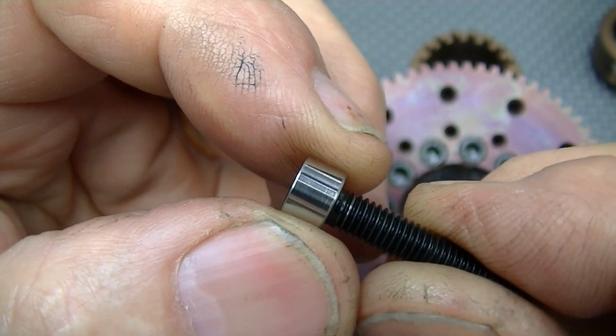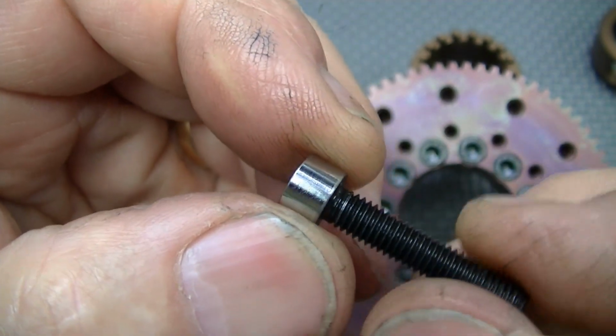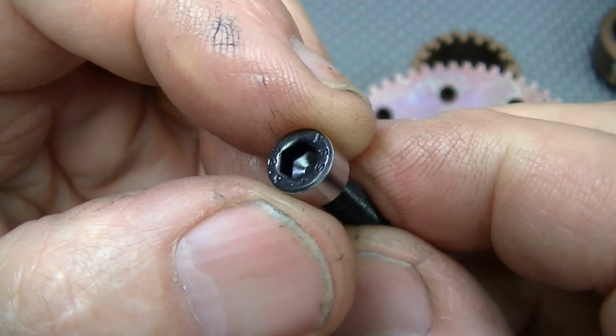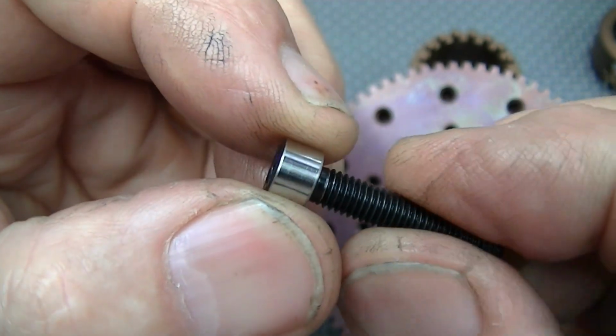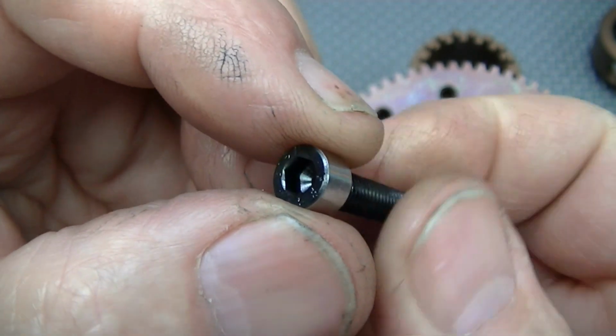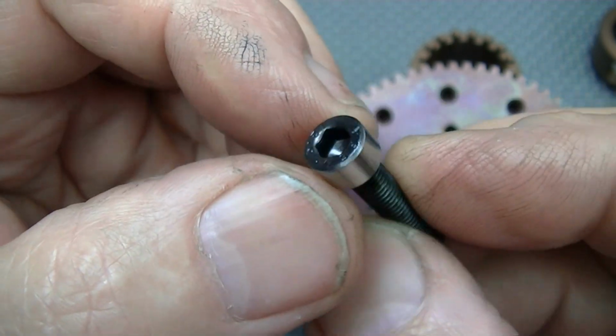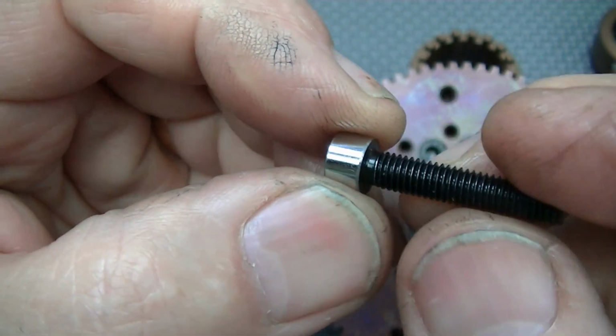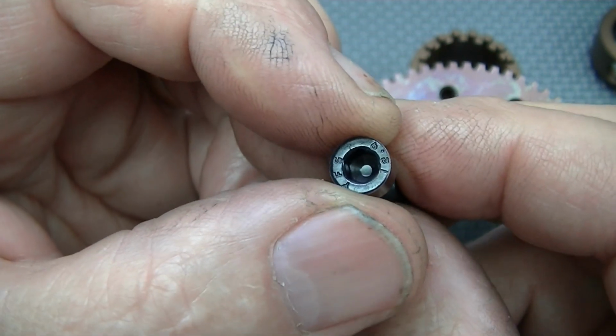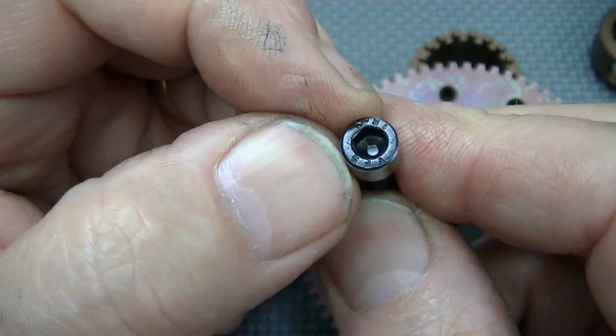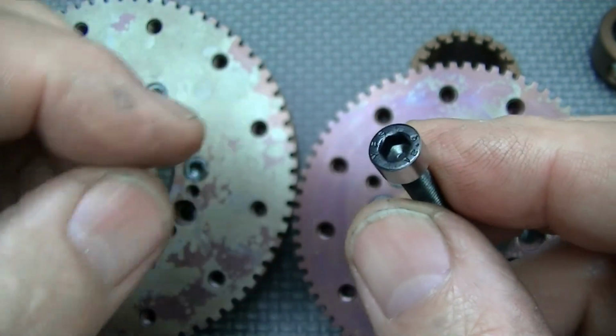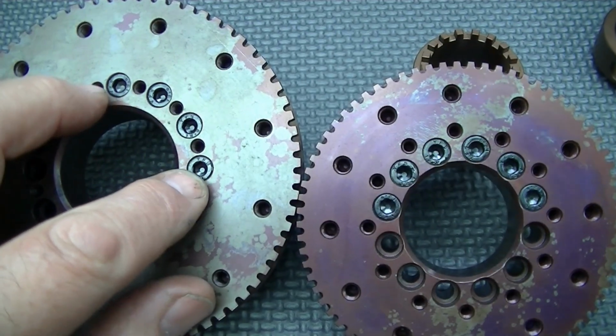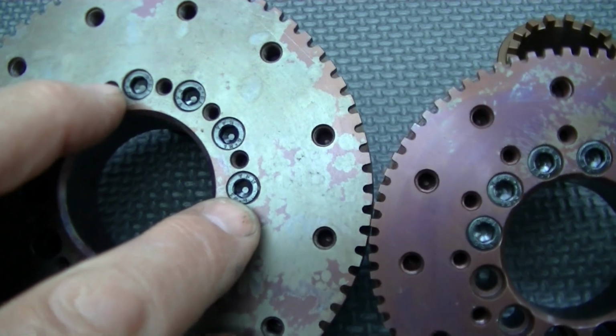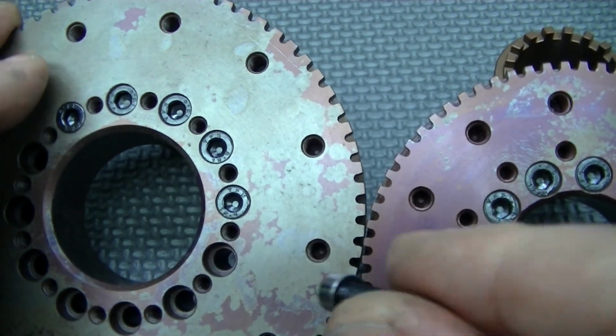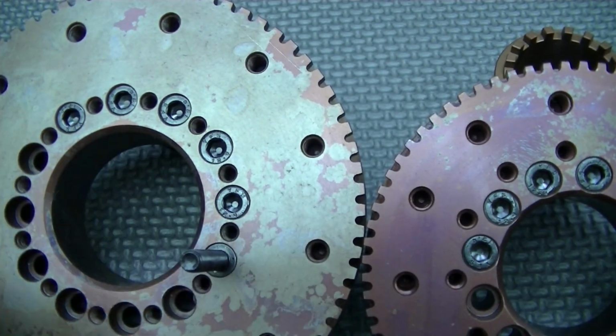Here's a technique that wouldn't be recommended for mass production, but for specialty tool room items. One technique I like to use is turning the heads of socket head cap screws to a nominal size. In this case, I turned the head of an M5 socket head screw down to 5/16 of an inch, 0.3125, from its original 0.359, I believe, diameter. The purpose of that is so that I can do a very precise fitting counterbore that only has a few thousandths of clearance. These only have about 2 thousandths clearance, and that does several things.